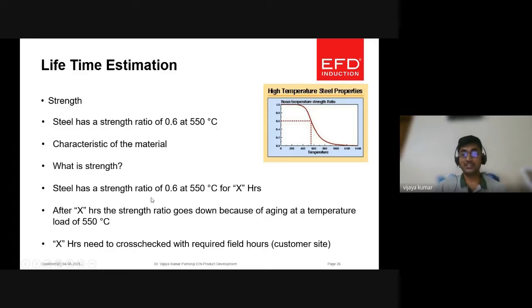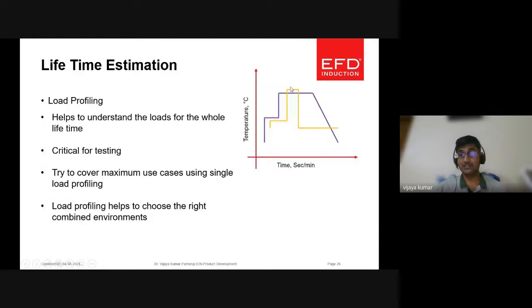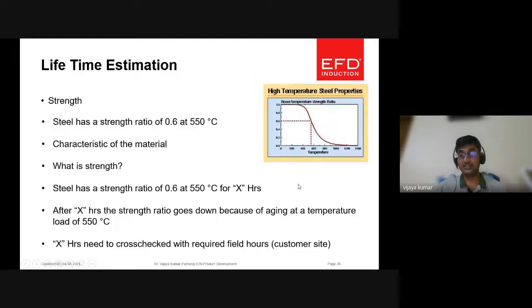Again, steel has a strength ratio of 0.6 at 550 degrees centigrade, for X hours. Again, time. Based on my load profile, I have to see whether they need it for 10 hours or 2 hours. As I said, here it went to peak. Now I have to match whether it can withstand this X hours. So I have to cross check all the time. After X hours, the strength ratio goes down because of aging at a temperature load of 550 degrees centigrade. X hours need to be cross checked with the required field hours. As I said, we need to look into the customer load profiles to match the material strength.